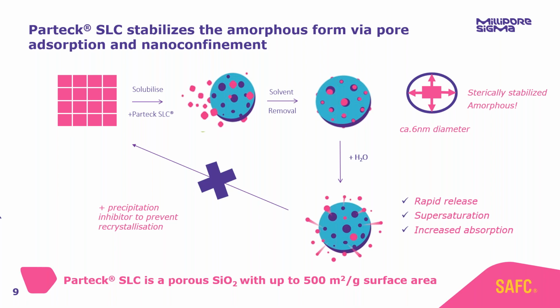The molecule wants to precipitate out of solution and recrystallize into that thermodynamic equilibrium of the crystalline solid in solution. The silica at this point has no impact whatsoever on maintaining the supersaturation of that system. And so therefore, an additional component is required, known as a precipitation inhibitor, usually a polymer, which maintains that supersaturation so that absorption can take place over physiologically relevant timescales.